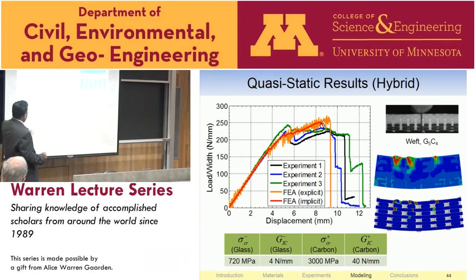Our results are able to capture the progressive kinking that occurs on the top side when we put glass on the top and carbon at the bottom. You can see those red marks are those kink bands that form on the homogenized scale.